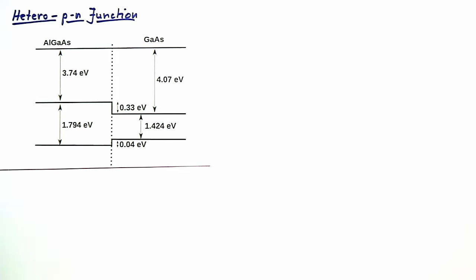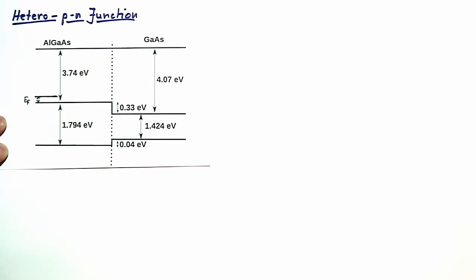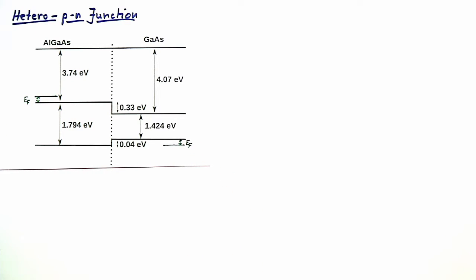The problem states that we should assume the aluminium gallium arsenide material is degenerately n-doped, whereas the gallium arsenide material is degenerately p-doped. Thinking in terms of an electrochemical potential or Fermi energy, we therefore need to draw in aluminium gallium arsenide a Fermi energy above the conduction band edge, while since gallium arsenide is p-type, the Fermi energy would be down near the top of the valence band.